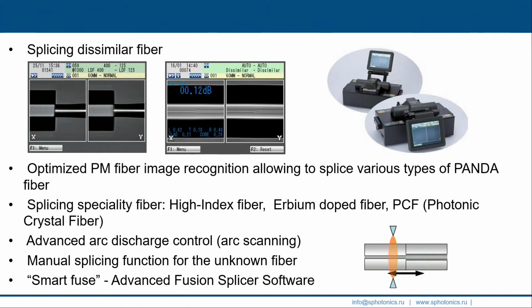We can see here on this image that actually the splicing machine, the splicing tool, is using the method of scattering pattern analysis. So we just illuminate the fiber with the monochromatic plane wave, and then on the camera we can see here not the profile of the fiber, but the scattering pattern, the diffraction pattern. So if we use some kind of fiber with stress rods with compensated refractive index, we just need to use some additional equipment to know exactly the position of the birefringent axis during the splicing process.